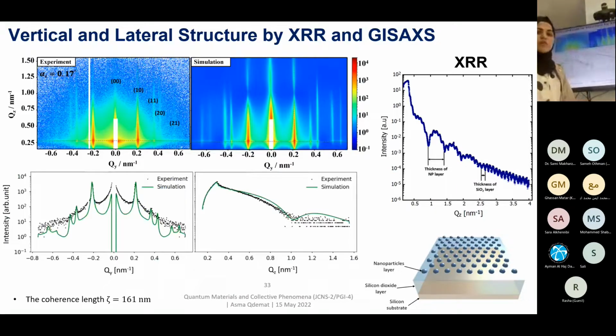We also performed GISAXS on this sample to study the in-plane lateral order of the nanoparticles, and we obtained Bragg rods along Qy, which are due to the in-plane ordering between nanoparticles. The Bragg rods are indexed assuming a 2D hexagonal lattice. Also, we simulated the system using BornAgain software, assuming only a hemispherical particle shape, a 2D hexagonal lattice, and some random orientation of the domains. Comparing the horizontal and vertical line cuts, we see that the vertical line cut is in good agreement.